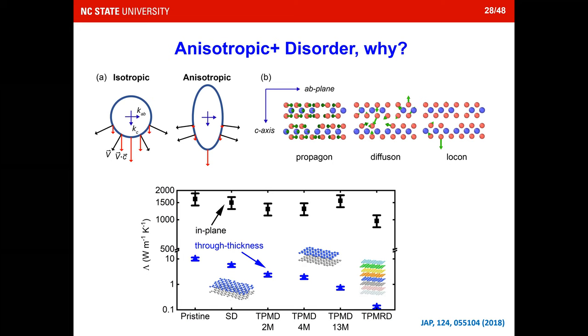We just have graphite layers. We assign different masses to them to create a disorder. We're trying to see, even by the simple disorder in this anisotropic material, can we actually achieve a much, much lower thermal conductivity than it should be? It turns out when you apply different disorders, as shown in the bottom figure, you can continuously suppress the thermal conductivity in the cross-plane direction without changing much in the in-plane direction. So this is entirely possible, right? And then, okay, this is not a realistic material. We know that. So we need to search for real materials. Can we actually push the limit of low thermal conductivity?